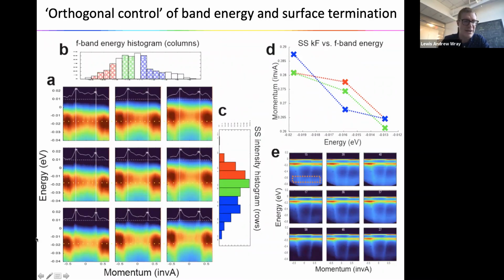In the case of samarium hexaboride, again, a fun thing for us is that we can dope the material. Because of the complexity of the surface of this material, there were no previous doping dependent studies, and we're able to separate out the density of samarium versus boron at the surface on this vertical axis versus the amount of electron doping on the horizontal axis.